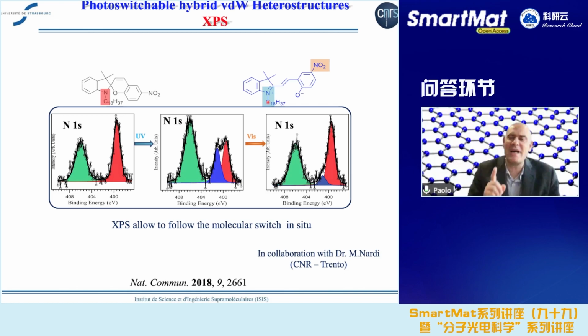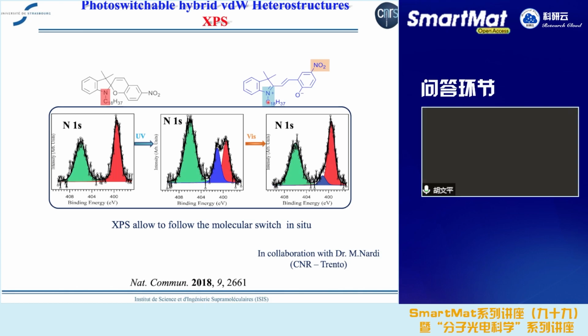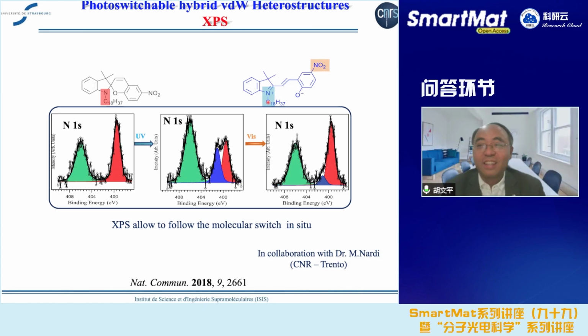Also, if I can add one thing, azobenzenes are slow switches, okay? So if you want to do digital electronics, azobenzenes are not very fast switches. For example, diarylethene, where you need to use a different type of mechanism for the doping, is much, much faster. We switch on the picosecond time scale, okay? So that is very good. Picosecond is very fast. Yeah. Thank you. Yeah, thanks. Okay.